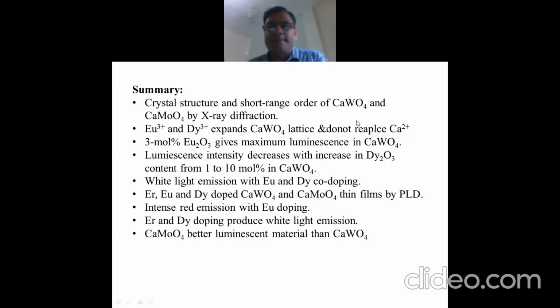There's one more question from Dr. Karthik. Which one, nanoparticle or thin film, is more effective in LED applications? We have found that between calcium tungstate and calcium molybdate, calcium molybdate is a better material. Its luminescence intensity is almost 3 times higher for all the samples with all the dopants. Thank you, sir. There's no more question. Thank you.